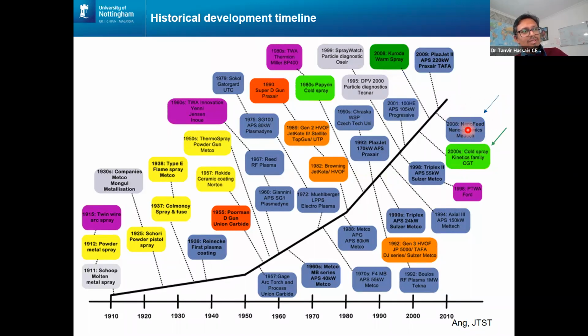And another new technology came in, which was called ceramic suspension spray or suspension plasma spray. All the things I've talked about so far use powder. Nanofeed and nanoceramic is a bespoke system from Mettech in Canada. What that allowed us to do is inject fine particles or particulates less than 5 micrometers. When particles are less than 5 micrometers, you can't easily feed them using a conventional powder feeder, so you need special equipment. And the talk is going to cover a little bit of suspension plasma spray, and a little bit on cold spray.